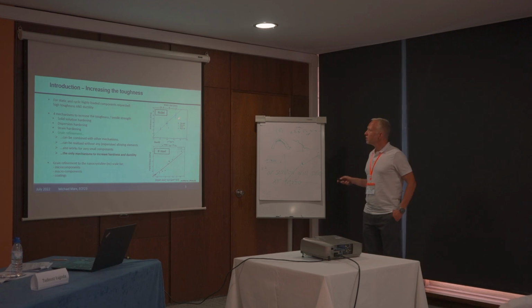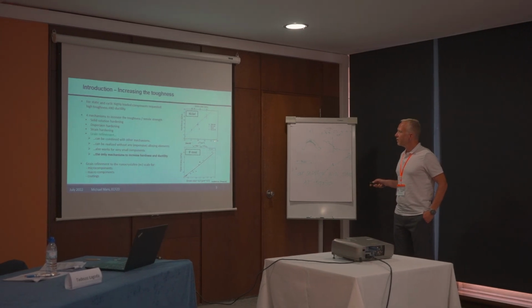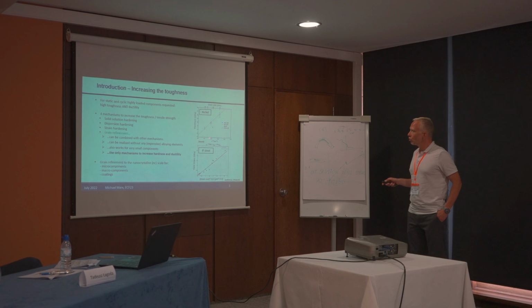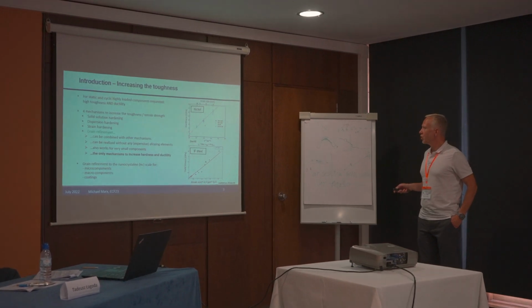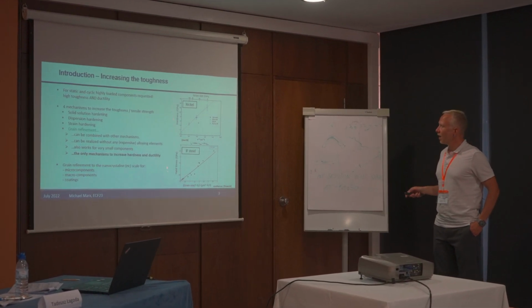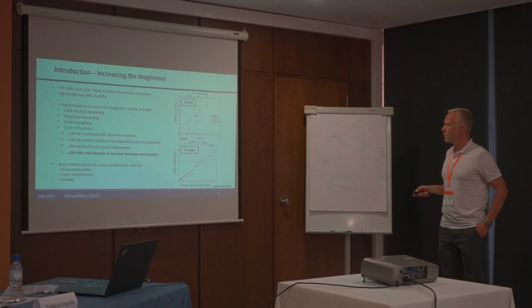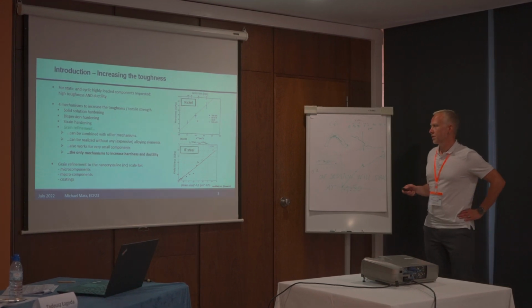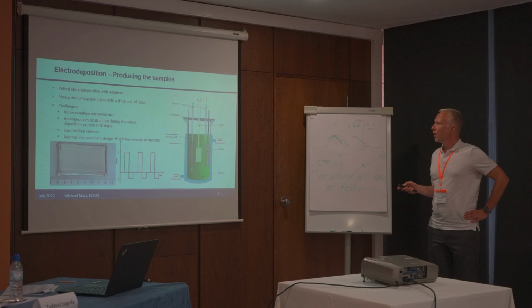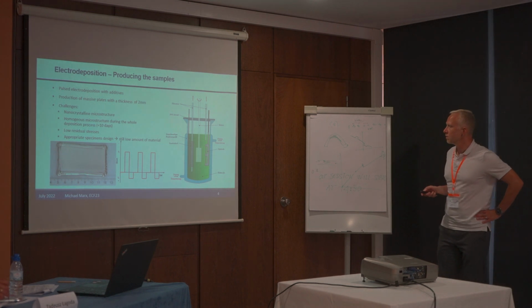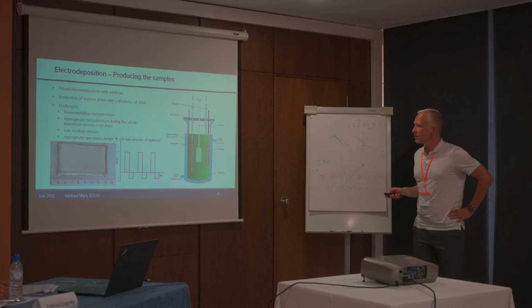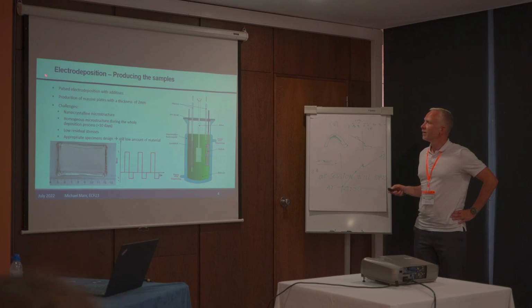And you know these Hall-Petch plots where we have the square root of the grain size, and here at this end we have the small grains, and here we have the larger grains, and we have an increase in hardness and an increase also in the yield stress. Yeah, what are we doing? We are producing our samples by electrodeposition. Here you can see a scheme how this looks like. This I have shown on the first slide.